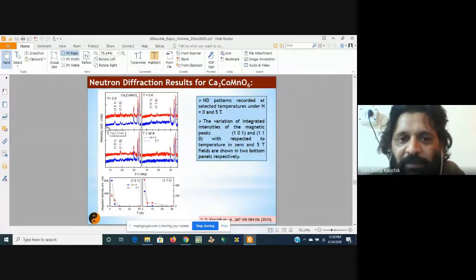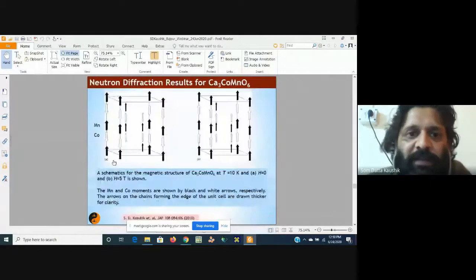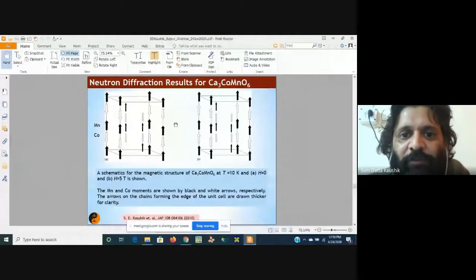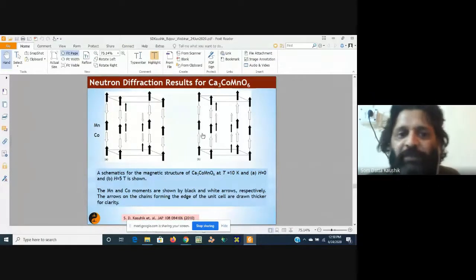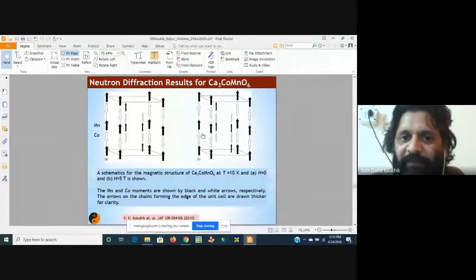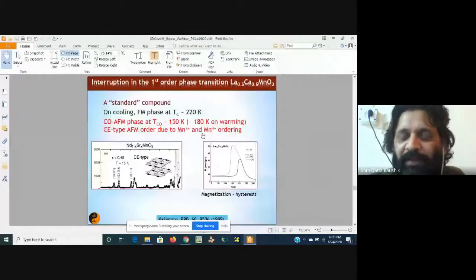But when we apply a 5 Tesla magnetic field, we can see this is in zero field and this is in 5 Tesla. So these are Mn spin and cobalt spin. Upon the application of field, we can see the spin of cobalt is flipping along the Mn direction. So by application of field, we were able to flip the magnetic spin of cobalt. So the idea is that by applying magnetic field in a neutron diffraction study, you can see whether your field is strong enough and playing some role in changing the structure, and you can understand that very carefully. If time permits, I can show you a few more examples. Otherwise, we can finish here.